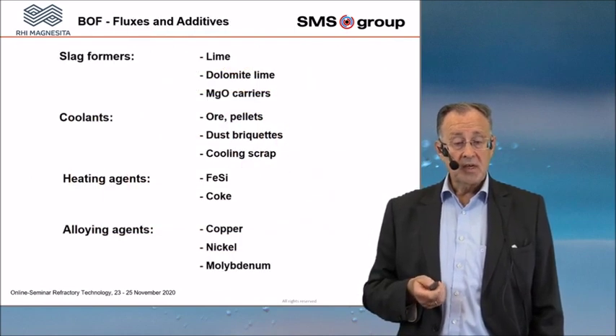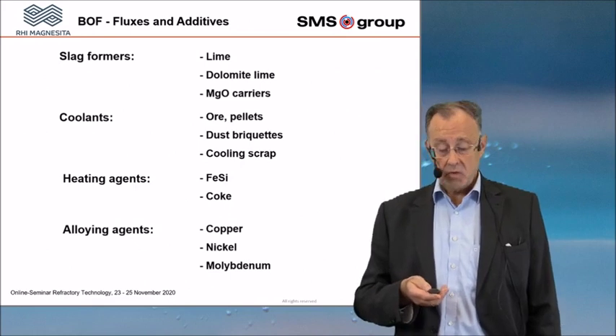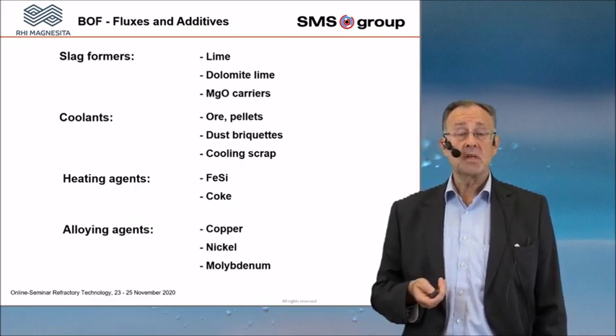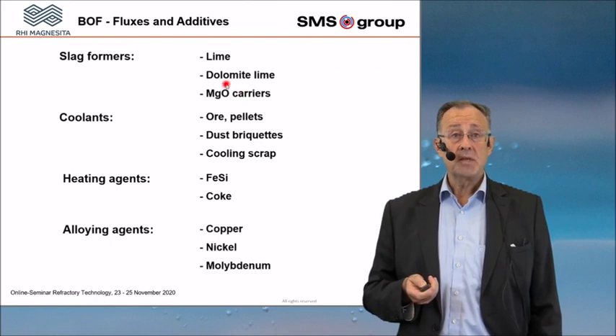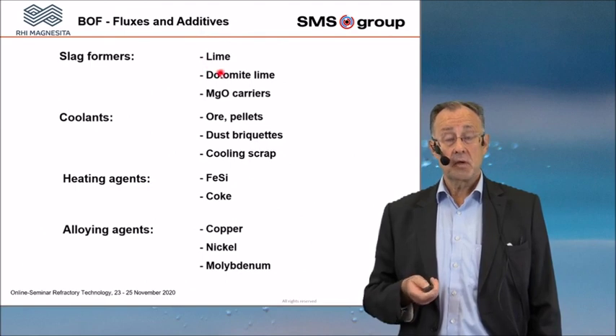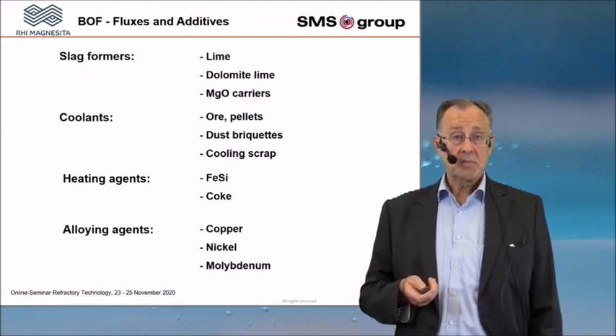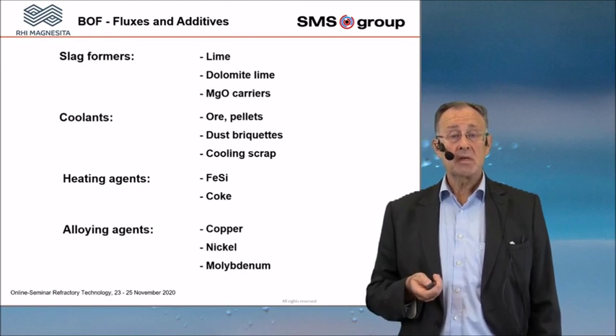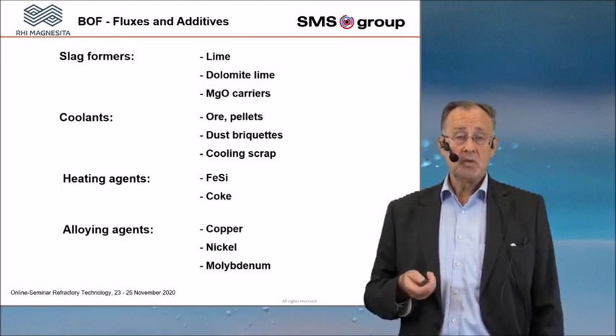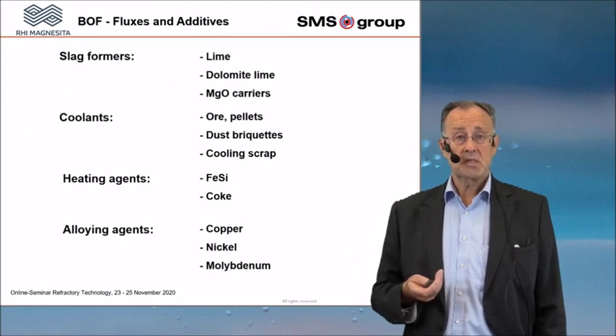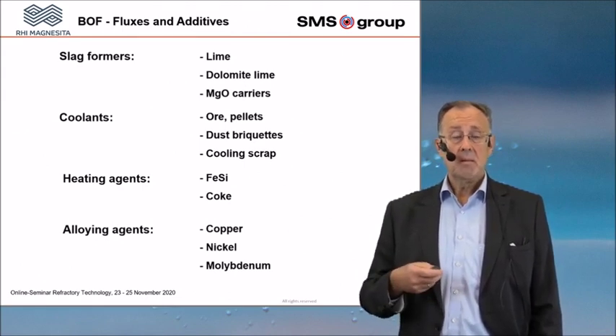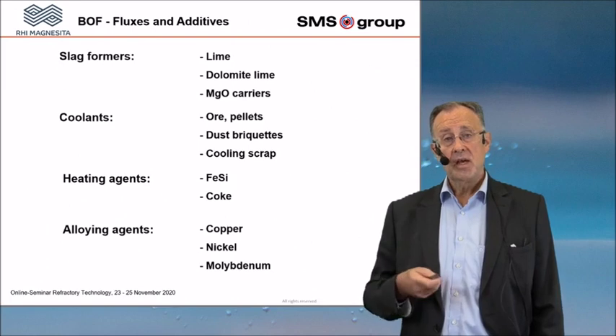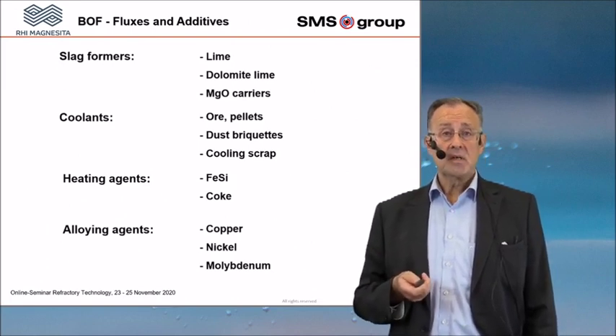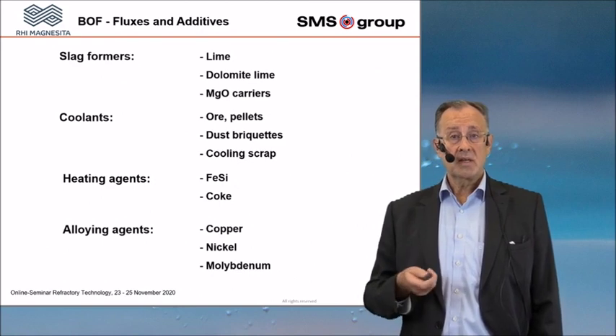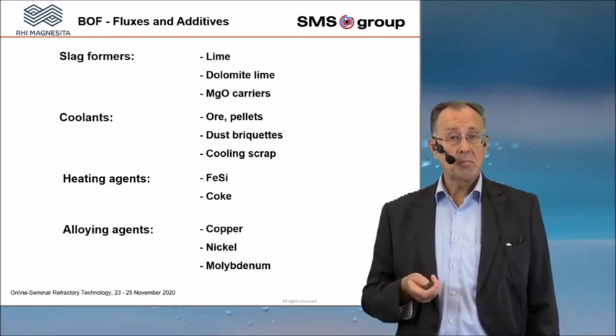So what are the additions and additives you add into the converter? And at first, very important is that you have here all the slag formers where you put it in the converter. That means the main portion is lime, or sometimes dolomite lime or MgO carriers. This is very important because you need the slag formers, because all the oxides you produce during your blowing process must be caught and bound in the slag. And for this, lime is absolutely necessary, so that you can collect all the oxides coming out of your blowing process.